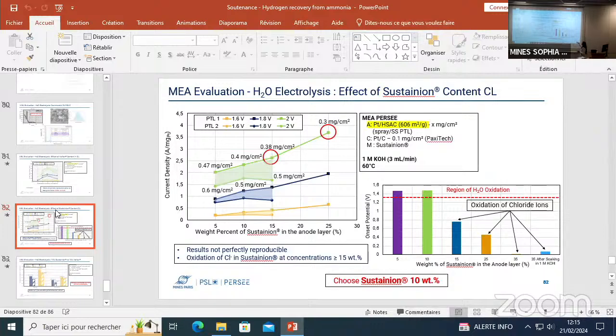What I tried to do is take this test, where I had 35% weight of the Sustainion in the anode layer, and then I did a specific treatment, which is immersing the MEA in 1 molar KOH, and then I redid the same test. I had a slight increase in the voltage, which could mean that we removed more of the chloride that should have been removed, but it wasn't the right conditions, not the right time, maybe it needed longer times. So I said, okay, let's put this aside. It needs more treatment, more analysis, or finding the best conditions to activate the Sustainion without having chloride.